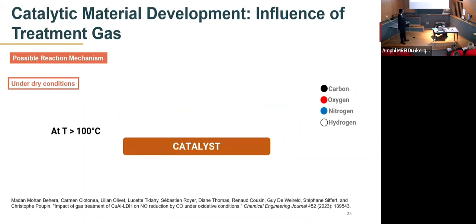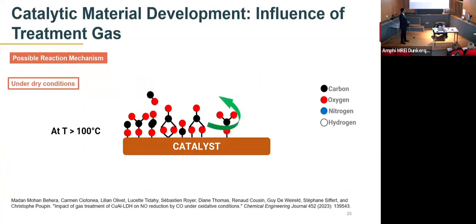When we increase the temperature to more than 100 degrees Celsius, these nitrate species can be replaced by the carbonate species, and these monodentate carbonates generally can dissociate to form carbon dioxide. At the same time, the nitrogen monoxide that is adsorbed on the surface of the sample can react with the oxygen, again coming from our gas stream, to form nitrogen dioxide. This is why we have nitrogen dioxide in our mixed oxide samples.